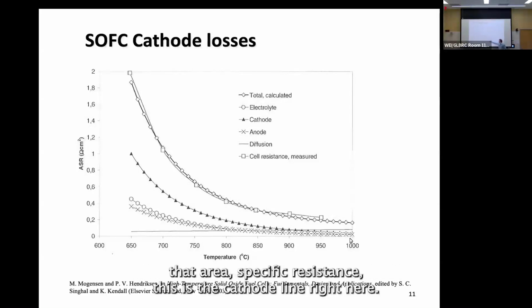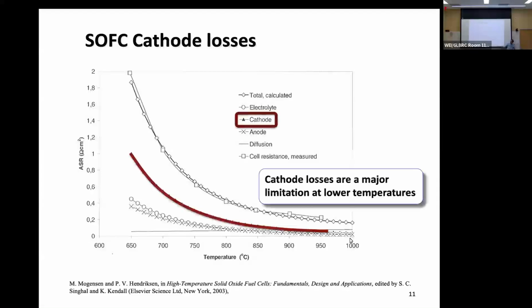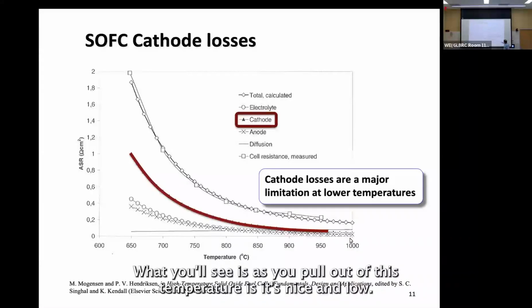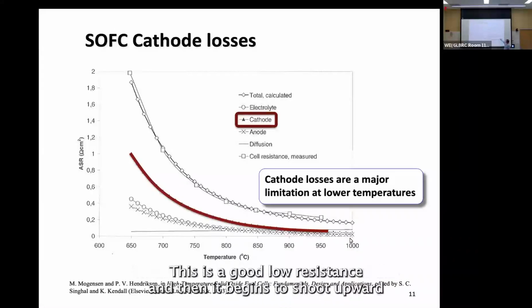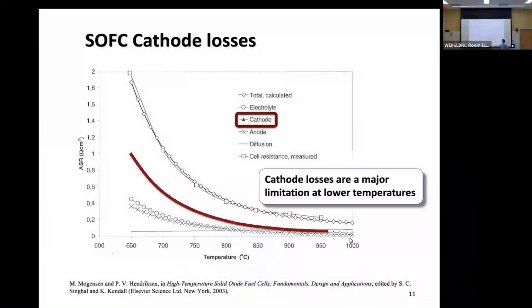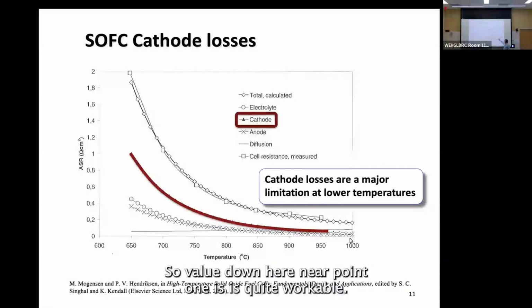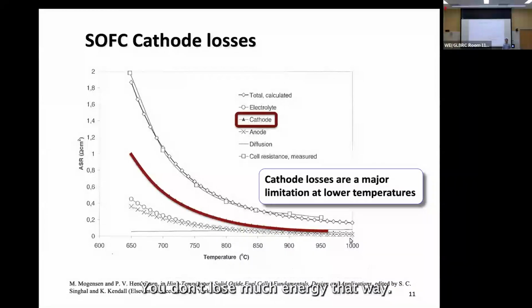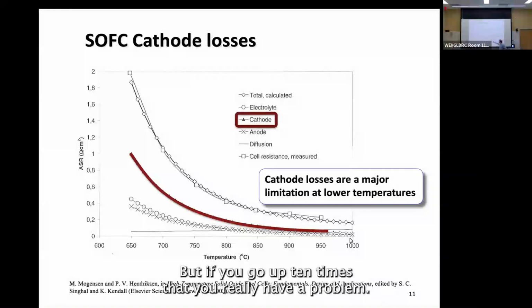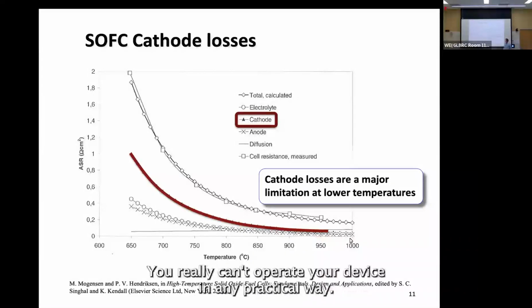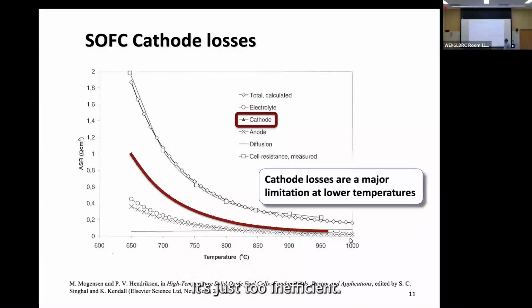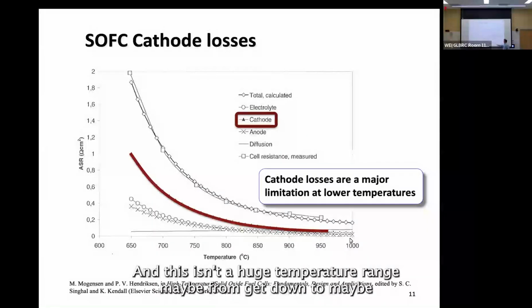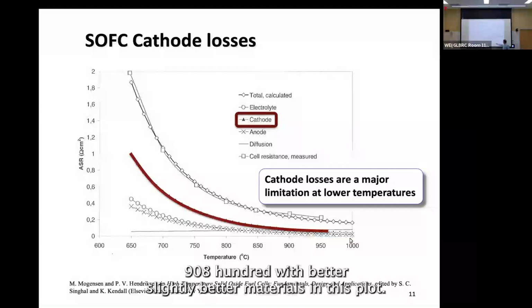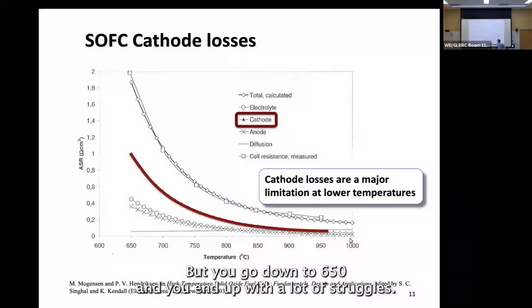And if you plot that area-specific resistance, this is the cathode line right here. What you'll see as you plot it versus temperature is it's nice and low. This is a good low resistance. And then it begins to shoot upward near 650, 700 degrees Celsius. So a value down here near 0.1 is quite workable. You don't lose much energy that way. But if you go up 10 times that, you really have a problem. You really can't operate your device in any practical way. It's just too inefficient. And this isn't a huge temperature range. Maybe you can get down to 900, 800 with slightly better materials in this plot. But you go down to 600, 650, and you end up with a lot of struggles.